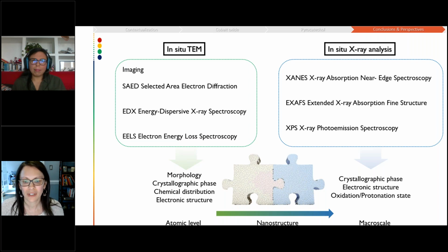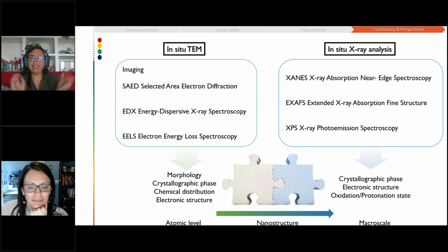Did you observe a dependency of the electrochemical response on the thickness of the liquid layer? We didn't measure the liquid thickness. We only could use the parameters that we could handle, like the electrolyte flow and the spacer, which was minimum 500 nanometers because of the electrodes. So we try to always use the same parameters, but I wouldn't say that we controlled the thickness of the liquid in order to verify that it would change the electrocatalytic activity. But the times that we could see better, of course, is when we had bubbles. In those cases the thickness would be smaller, but we didn't see an impact on the